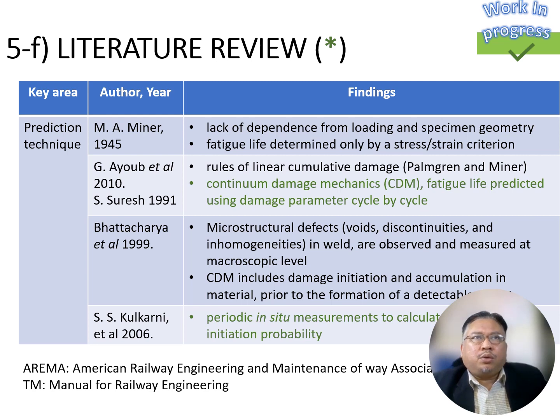it must be included with continuum damage mechanics, where all the fatigue life is predicted using a damage parameter cycle by cycle, and continuum damage mechanics includes the accumulation of damage from the very beginning until the end, which is value added to the linear cumulative damage. Bhattacharya et al. 1999 agrees with continuum damage mechanics because damage initiation and accumulation in material are important to be part of the damage formulation before detectable defects happen at the microstructure level. CDM includes damage initiation and accumulation in material prior to the formation of detectable defects.